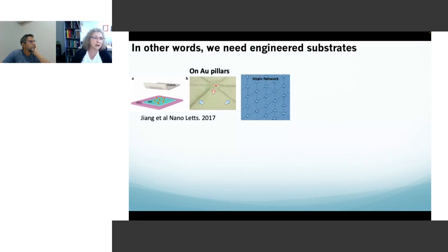And this is a picture of how graphene looks on top of each of these pillars. These pillars have a diameter of 100 nanometers roughly. So graphene on top of the pillar is rather flat, and the strain is more pronounced when graphene falls from the pillar. And if you look at the micrograph of a larger structure, you see that the flat areas are identified by these circles here. And between the circles, we have these folds forming, okay? It's pretty much similar to when you have a bed sheet and you hang it outside to dry in the sun. The folds that form resemble pretty much what happens on graphene.